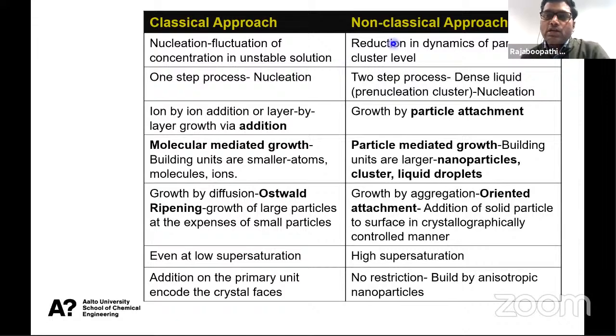And again, these are some differences between the classical and non-classical approach. In the classical approach, nucleation is formed by a concentration difference, or we can say fluctuation of concentration in the unstable solution produces nucleation. In the case of the non-classical approach, there is a reduction in the dynamics of particles to produce a nucleus. Here, it is a one-step process. Non-classical is a two-step process.